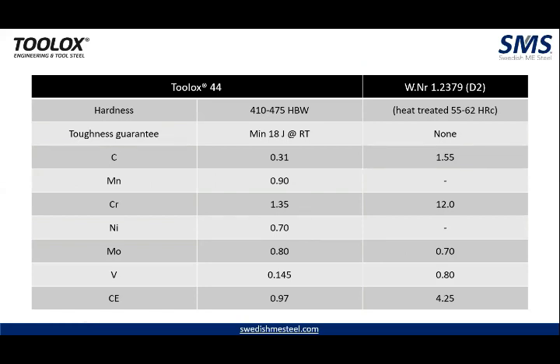As I have deliberated earlier, the higher the toughness value of the material, the better is its ability to resist cracking of the die. So if your die has been made with Toolox, and if you are having cracking issues in your previous die, Toolox 44 can immediately address this issue without any doubt. So it's a low alloy material, and once again the carbon equivalent is less than 1 for Toolox, which is way, 4 times higher for D2, which in turn helps you in easy maintenance of the die, as well as thermal cutting is also possible.